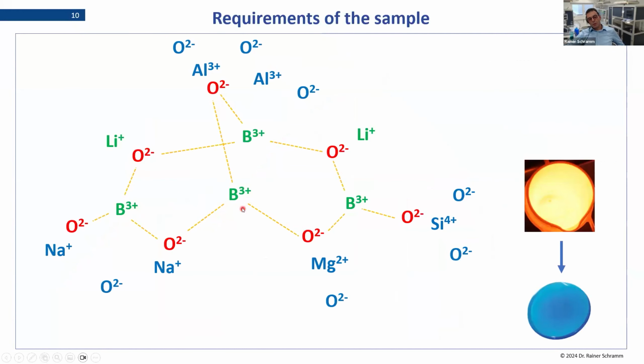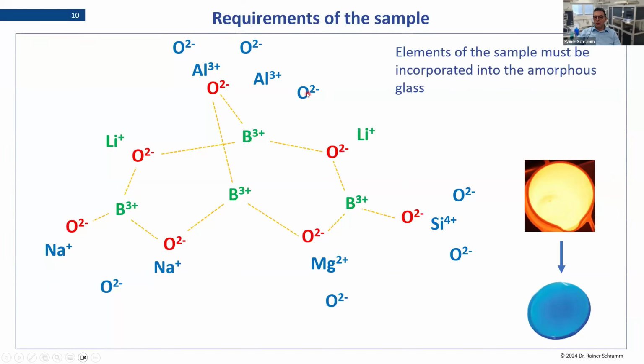So this is perhaps how we can think about how it behaves in a liquid glass. You will have this arrangement of boron cations and oxygen anions, which are in a certain relationship to each other. And then the sample with all the elements is just sitting in between. Because it's liquid, it's all moving fast. But what we have to learn out of this is we need an oxidic sample so that it can dissolve into glass. A metal or any reduced species like sulfide, nitride or carbide is not able to interact with our lithium boron oxide. Therefore, it is very important to know that we need an oxide.